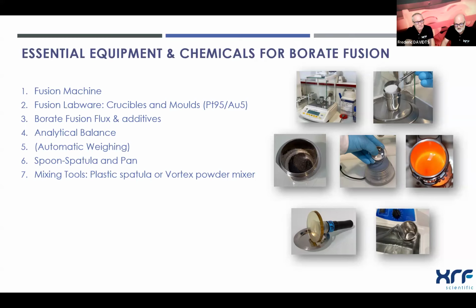spatula, of course, and vortex mixing tools to mix the flux and the sample before the fusion. That's really important, to start already with a homogeneous mixture to save time and avoid material agglomerating in the bottom of the crucible. A micropipette is needed when you are using the non-wetting agent in liquid form. You cannot just add drops with a dropper. You need something to measure perfectly the quantity you have.